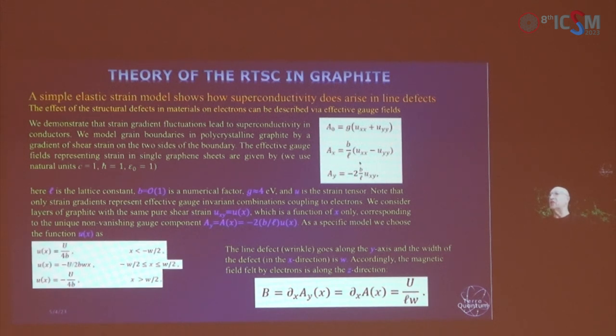We consider layers of graphite with the same pure shear strain, which is a function of, let's say, the coordinate perpendicular to our wrinkles. Then we have a unique non-vanishing gauge component, and the specific model for the strain is given here. It is just a simple model, which very well models the behavior of strain in the wrinkle, and then we immediately obtain an effective magnetic field, which is related to the wrinkle and is felt by electrons. It is directed perpendicular to the graphite plates. This is the final formula here.